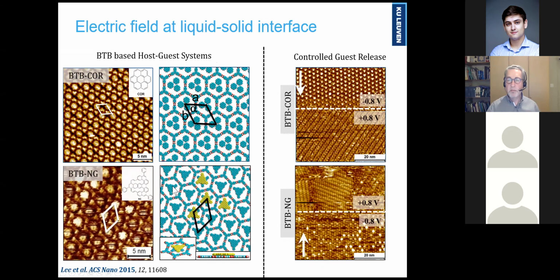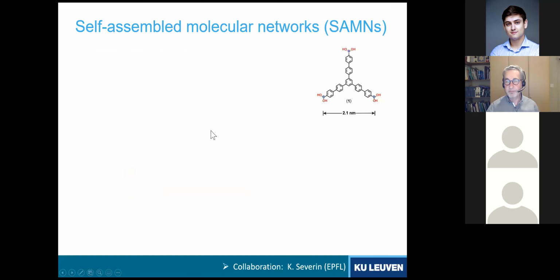The point I want to make is that indeed now, starting from a situation where the so-called guest molecules are trapped into the porous network, by changing the polarity we can go from the porous network with the guests to the non-porous network, meaning that the guests have been expelled from the network. And that's a first kind of functionality at the level of these supramolecular networks.